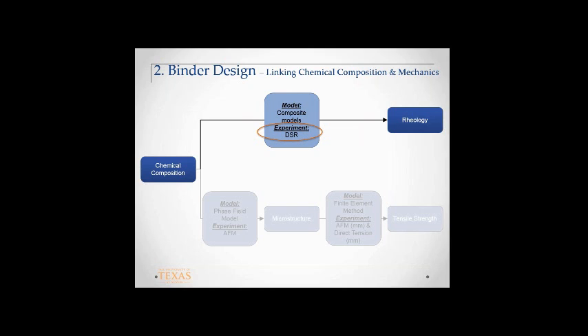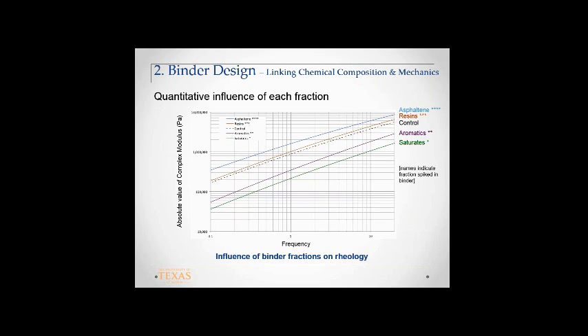You start with experiment. Let's measure the rheology of this stuff. You measure the rheology and get what you have here, the master curve. On the y-axis you have the complex shear modulus, and on the x-axis you have the frequency. You can see this was the original binder, the dotted line, and then we had the resins, asphaltenes, aromatics, saturates.